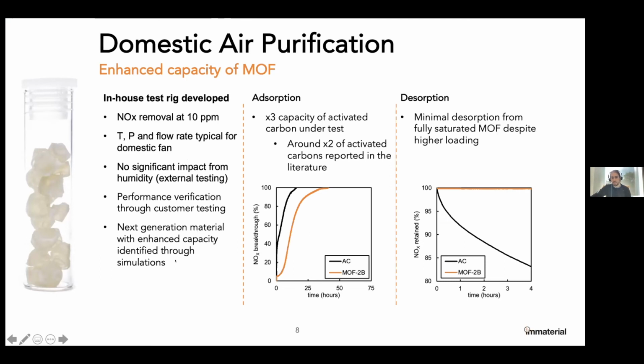And we've also worked with some of our customers, so some of those manufacturers of air cleaning fans, to verify our results versus their best available technologies. And alongside that, we've looked to identify next generation materials through simulations, and I'll share a bit of detail on that in a moment, which allows us to access structures which perhaps nobody else has ever looked at in these applications before. So in these, we ran breakthrough tests on these monolithic MOFs in our test rig, and comparing to an activated carbon, which was extracted from a commercially available fan, we matched our monoliths in particle size and distribution to those activated carbons, and you can see here we get around 3 times the capacity under these breakthrough tests with our monolithic MOF, this MOF 2B here.